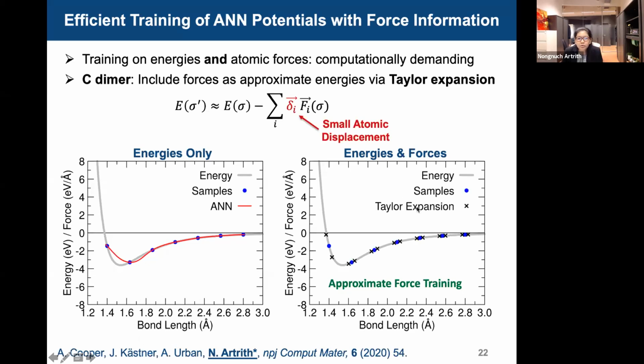But then we introduce more data points, using the Taylor expansion method and approximation. We introduce a few more data points. In this case, we introduce small atomic displacements like minus x and plus x, so we have more data points, and then we train neural potentials. It improved the predictions. You can see it gets the right atomic structures and also the right energies.